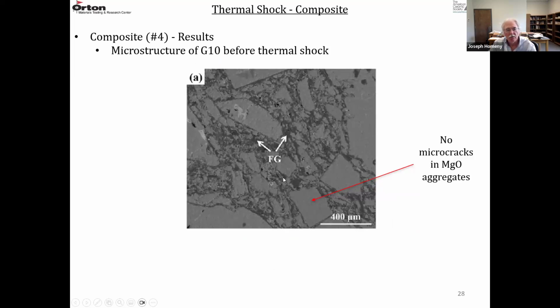So G10 before thermal shock. This is the sample without any pellets. These gray areas are the fused MgO grains. You can see some impurity here. The black areas are the flake graphite, and the flake graphite will bend and conform to the shape of the magnesium aggregates. So this is before thermal shock, and you can see the crystals of the fused cast MgO. There are no cracks in these crystals.